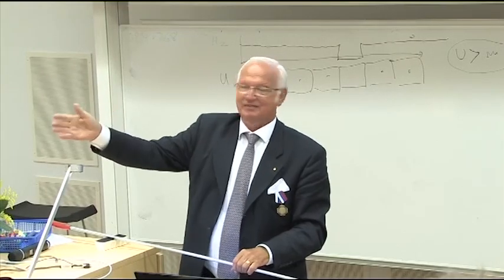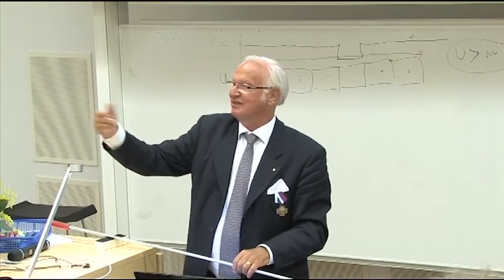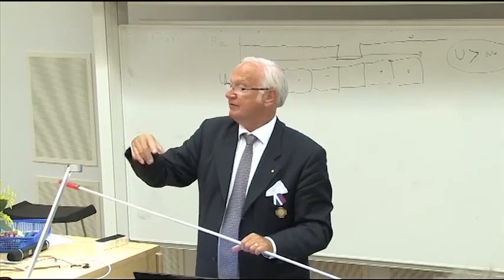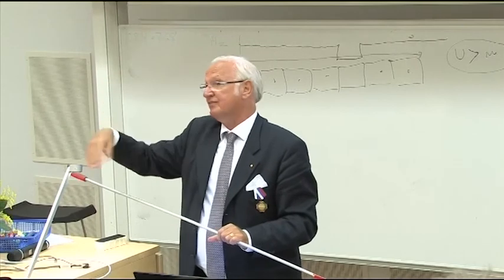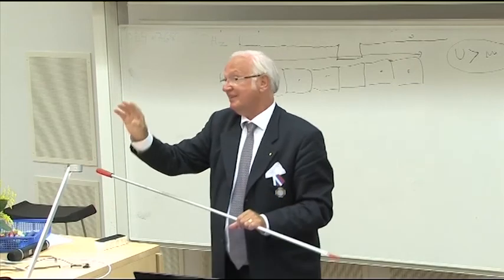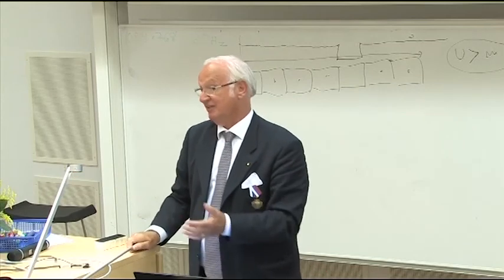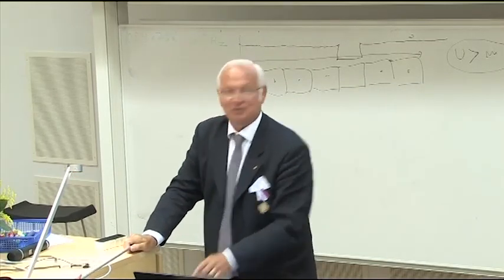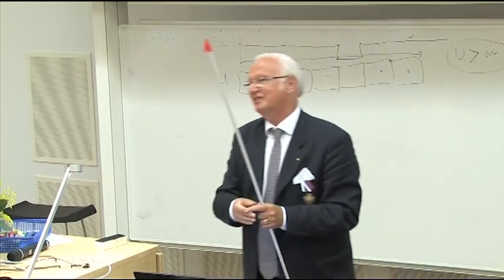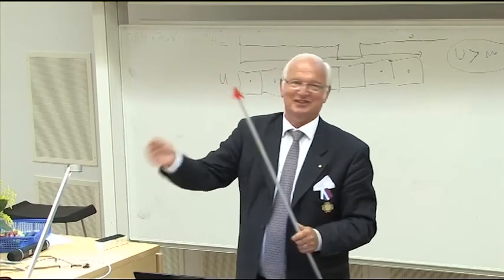Because what we see in cerium in this alpha prime phase is exactly what this fellow is talking about concerning this softening of the peculiar mode. We tried it also for praseodymium, and we don't see anything in the alpha uranium phase for praseodymium, nothing. So I think it's a very good signature of itinerant behavior in this particular case, at least. We have had two publications recently on cerium. This is really returning to good old times with a very good message.